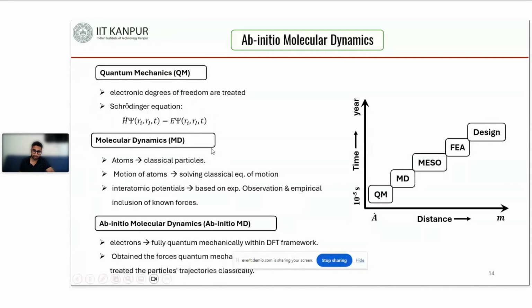And there is another method, molecular dynamics simulation, where atoms are treated as classical particles, and the motion of the atoms is predicted from an interatomic potential by solving the classical equation of motion, that is Newton's law. We need the interatomic potential to do the MD simulation, and these interatomic potentials are based on experimental observation and empirical formulas of the known forces, like van der Waals forces and electrostatic forces. Modern MD simulation has the ability to simulate a large number of atoms, or a supercell containing a large number of atoms, but it gives relatively poor accuracy. Also, for a new metal where you don't know the interatomic potential, it is very difficult to do MD. So there is another method called ab initio molecular dynamics simulation.